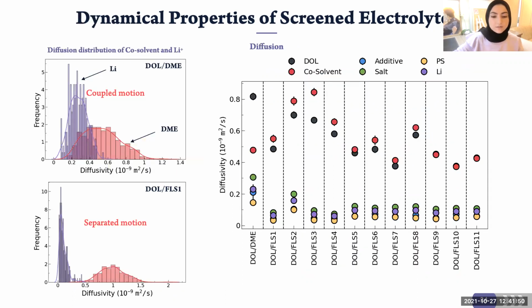We also examined the dynamical properties of each of the electrolyte systems, and this plot here shows the distribution of the diffusion coefficients of the cation and DME in the standard electrolyte, and we can see that there is some kind of coupled motion occurring here, which is consistent with the structural analysis performed earlier that showed that there is more coordination with the DME solvent with the cation in this system.